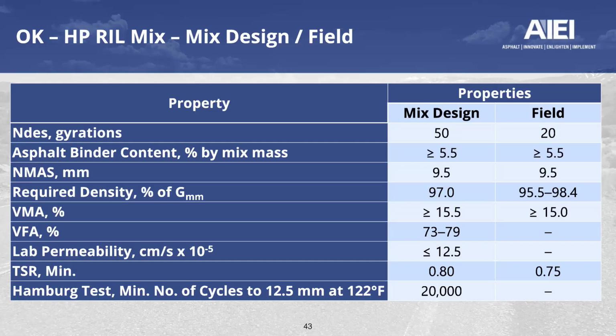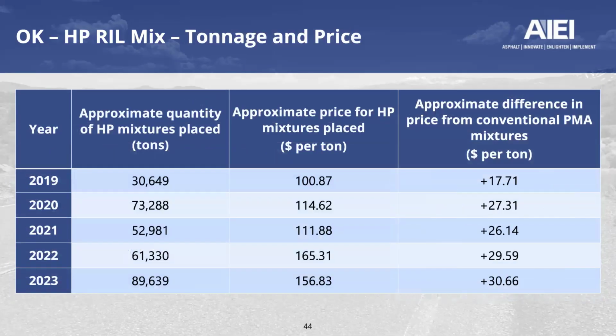It's interesting. They also are doing a TSR. This is the first state that we've seen that is looking at that, and they have an 80% requirement. They, as well as others, are utilizing the Hamburg. They are using their standard 50 degrees C's, 122 Fahrenheit, and a maximum of 20,000 cycles on that. 12.5 millimeters of rut, excuse me.